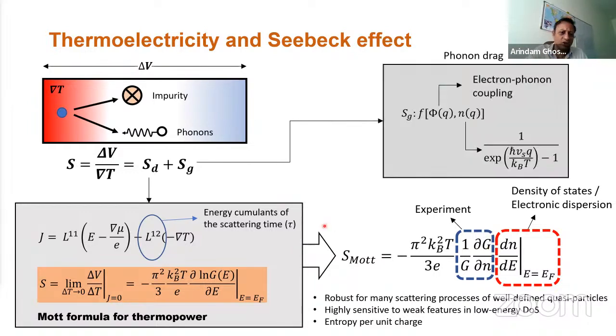There is also another part, which I'm not going to talk about today at all, which comes from the electron-phonon coupling, and it's called the phonon drag component of the thermopower. Instead, I'm going to use this expression where the semi-classical thermopower is proportional to the derivative of conductance with respect to energy multiplied by the density of states, and compare this expectation with what we actually obtain experimentally when we do this experiment with twisted bilayer graphene.